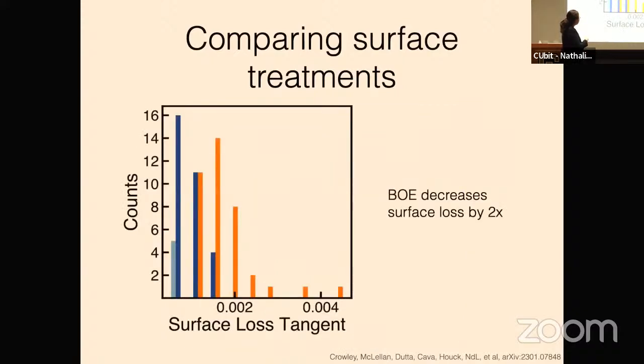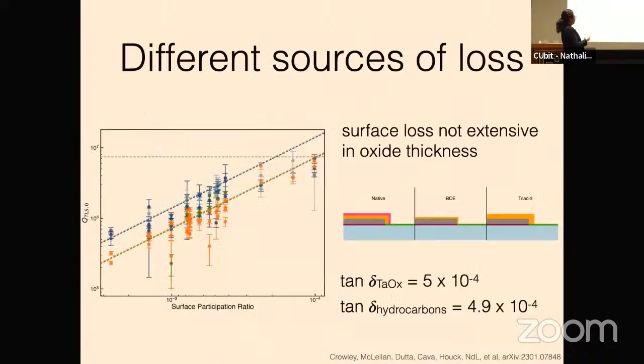Okay, so this is now a plot of that surface loss tangent, and you can see that this BOE decreases the surface loss by a factor of 2. The other thing that's a little bit surprising is that this Tracid data line, which is the green loss tangent curve, has an oxide thickness that's about a factor of 2 larger, but you can see that these points didn't go a factor of 2 down. So we have an oxide-related loss that is not extensive in the oxide, so you need to invoke at least one other TLS path. So one possible model is that we have oxide and hydrocarbons, and then both the BOE and the Tracid are really good at getting rid of these hydrocarbons, and then they sort of cancel each other out, basically, that you increase the oxide loss and decrease the hydrocarbon loss.